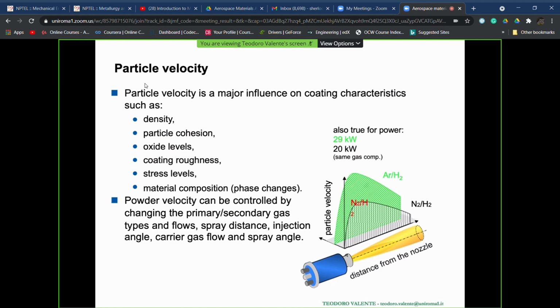for example, cohesion inside the coatings, that is between particles, oxide levels, in the case we are thinking of air plasma spray, for example, because this is the value, the particle velocity, with which we can calculate for how long the molten, for example, metallic-based particles can see oxygen in the atmosphere if it is present. It has obviously also a very